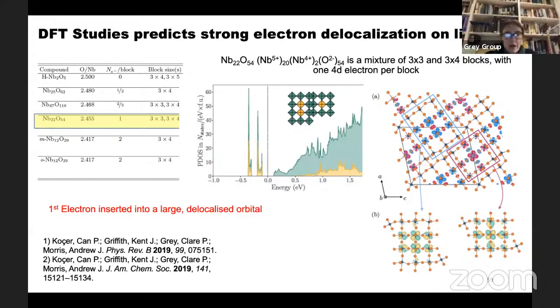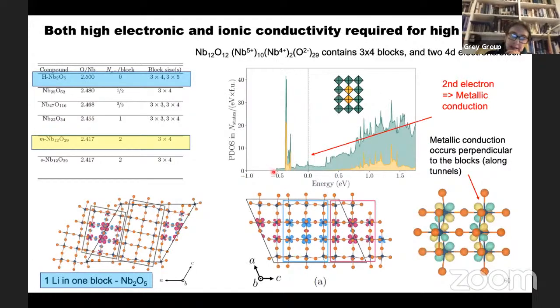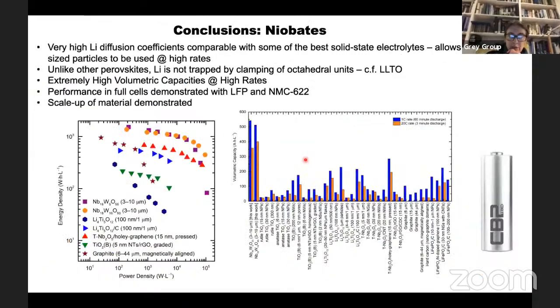So anyway, we do a lot of work in trying to understand why this works. And this is some work of Can Kosa and Andrew Morris looking at the theory of these things, trying to understand where the electrons go. One of the important things is the electrons go into bands that go all the way down these tunnels and give these compounds metallic conduction, which is another reason why they work very well. So in order to move lithium ions, you need to get lithium ions in and also electrons. And so this is an important part of the good materials performance. And so the bottom line is these are really very good performance, and we've just spun out a little company to try and see if we can enable their use in fast charging batteries.